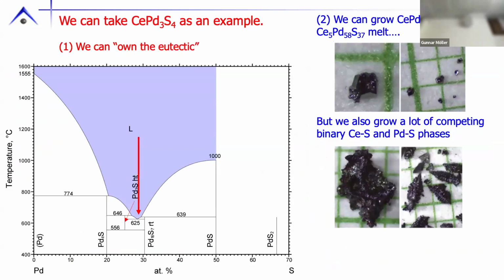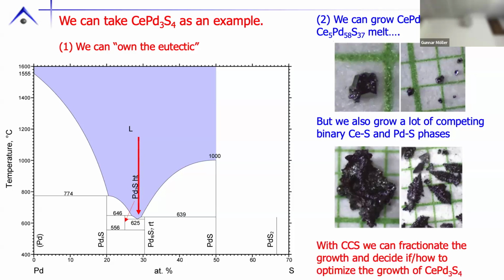We could own this palladium sulfur eutectic, we could work in it, and one of the first things we wanted to do is see if we could grow some of these rare earth CePd3S4 materials. The cerium's interesting, the europium's interesting, we did a lot of fun work on them. But when we first put in a little cerium here, we got the right phase, but the right phase was barely visible to the bare eye, and we got a lot of this binary cerium sulfide, palladium sulfide, oxysulfide stuff that we called crunchy critters. It's what we didn't want. Okay. So how do we improve?